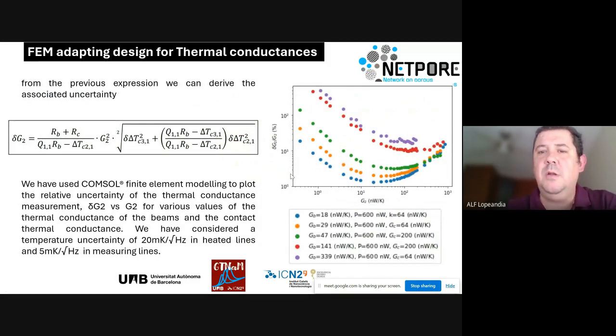Okay, from the previous expression, of course, we can derive the associated uncertainty and determine which will be the best parameters in terms of geometry of the suspended beams, depending on the thermal conductance of our nanowires. Our nanowires will be ranging between, I would say, 10 and 100 nanowatts per Kelvin, and we calculate, depending on the length, the shape, the width and so on, the thickness of the silicon nitride, which was the perfect structure in order to measure in that range.